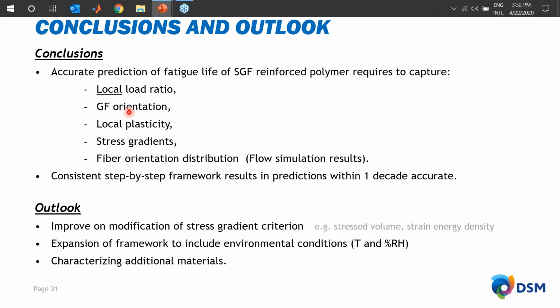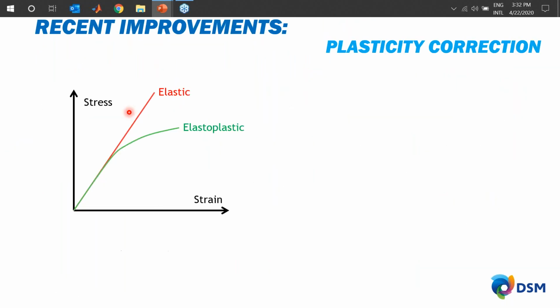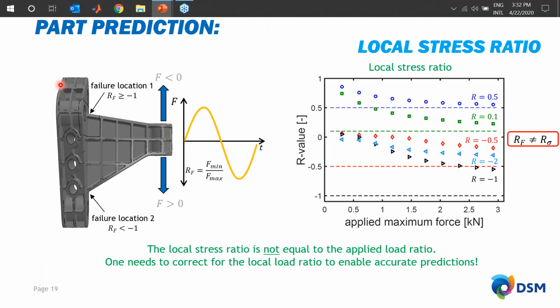Okay, thanks. Next question here. Is the local R ratio changing? Do you use a cyclic stress-strain curve? Yeah, we do not use a cyclic stress-strain curve. We were really surprised that the elastoplastic behavior, the quasi-static stress-strain curve, was sufficient to correct for this nonlinearity. But in all fairness, although it differs a bit depending on frequency or cyclic load, it's not that different from the quasi-static load. And the R value dependency, as we can show on this graph on the right, evolves as a function of applied load because of the asymmetry in the geometry. So it does not evolve as a function of time, because we don't update our stress-strain behavior, but it does change with applied load level. But you don't have any stiffness reduction or damage accumulation in the calculation included.